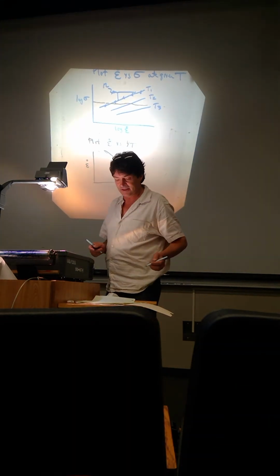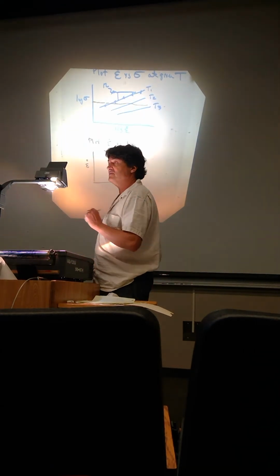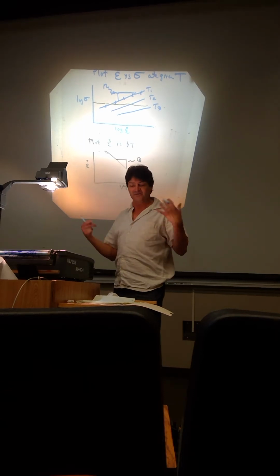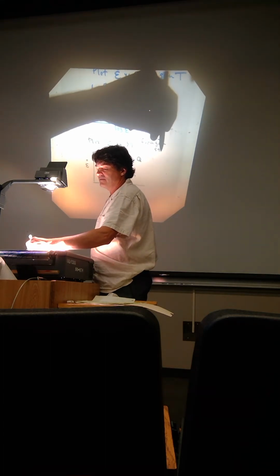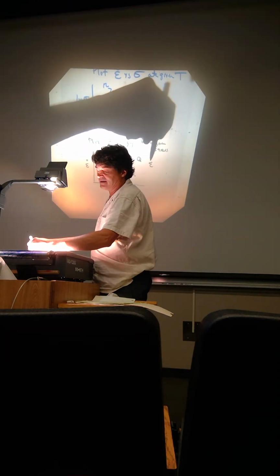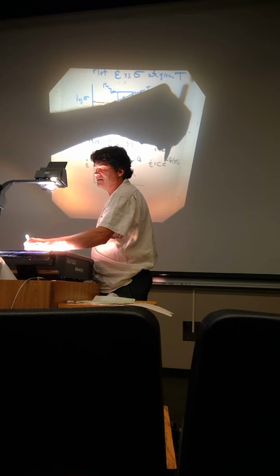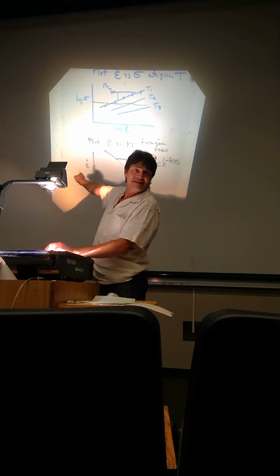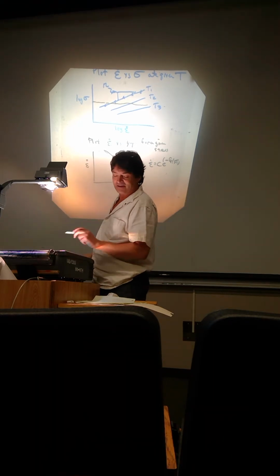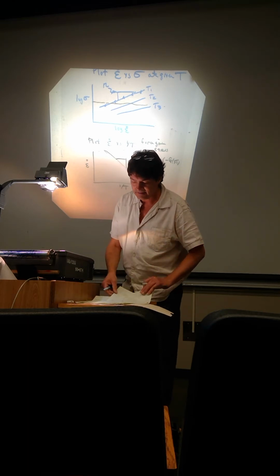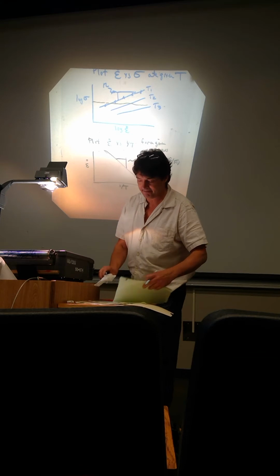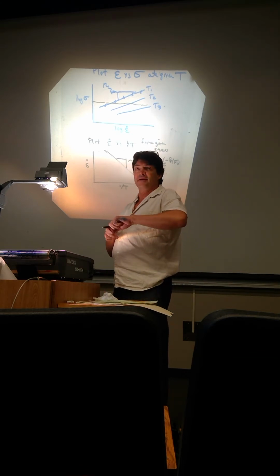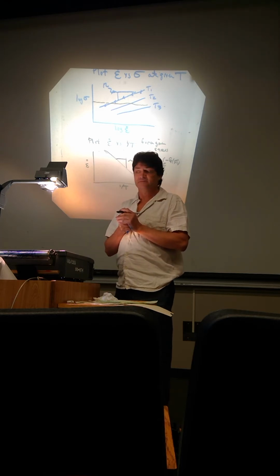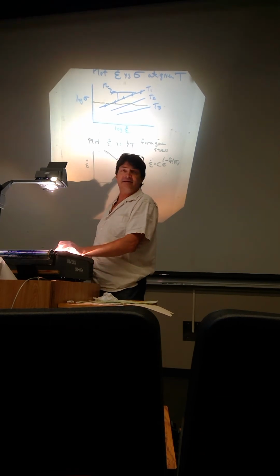The slope of this is proportional to Q, depending where you put your R and T when you solve this equation. So this would be for a given stress. You can simplify it and say strain rate is now equal to some constant C times e to the minus Q over RT. So this C is now incorporating a constant stress and an n, right? Since you're not changing that. So the slope of that is Q. And that's how you can experimentally determine the creep parameters that you need to know: your stress dependence n and the activation energy Q.